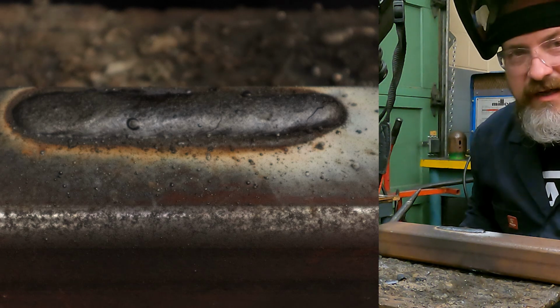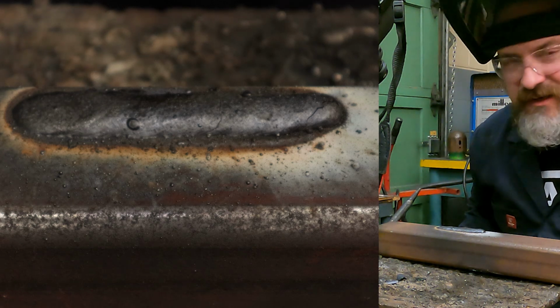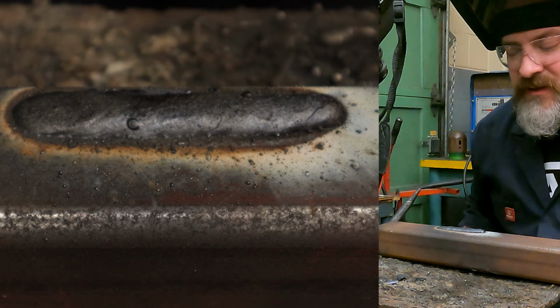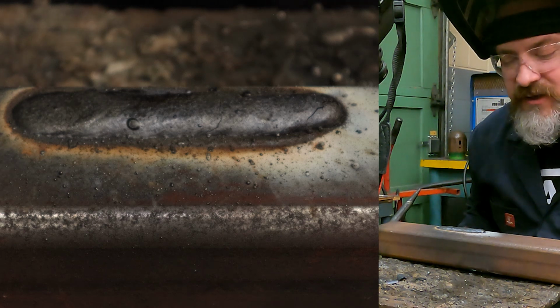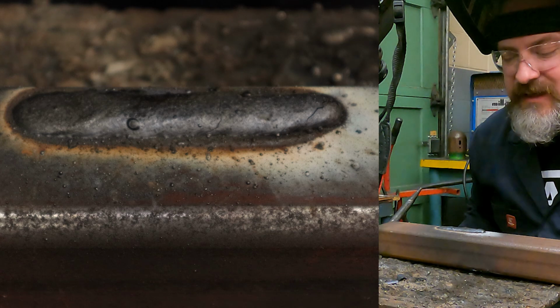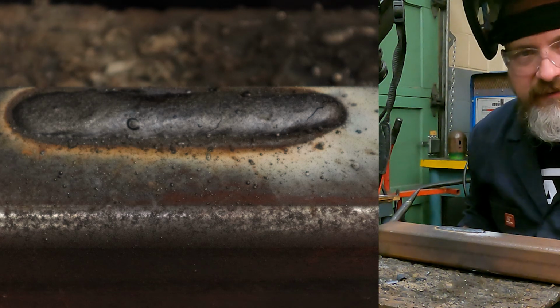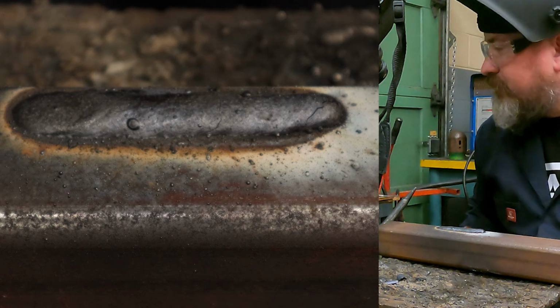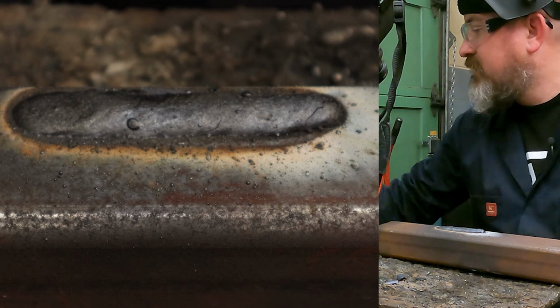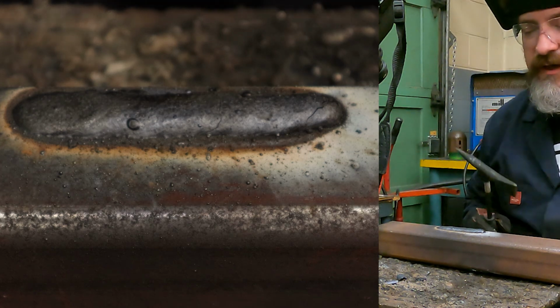If it tends to not want to come off and it sticks a lot and chunks are coming off but not all in one piece, you might have it set too cold and there's some undercuts where the slag is kind of sitting in and grabbing a hold of, or you might have some holes or some porosity going on. But if it's a nice weld bead, smooth, no undercuts, it should just come off.